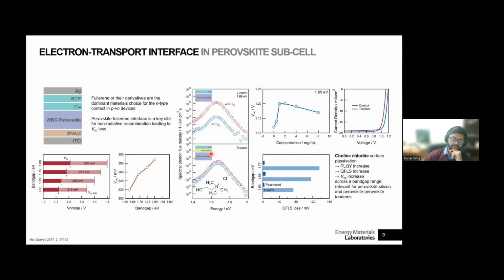Now, if you treat this interface with choline chloride, that's this molecule here, it's a quaternary ammonium salt. It's a very thin layer from a very low concentration. You'll see that here, this drop in the emission intensity is no longer there, right? They kind of overlap. And therefore, you can say that the non-radiative loss that you would otherwise incur in this interface goes down significantly. And we optimized this concentration for the voltage, basically, and we found this kind of a sweet spot, let's say at 1 milligram per milliliter. You can go a bit further, but not too much, because the current also drops a little bit. So this is kind of the best that you can get.